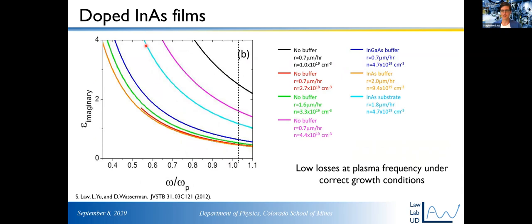And as a sidebar for any optics people who are listening, the imaginary part of the permittivity tells you about the optical losses, right? This is bad, right? You want to be able to shine light on your material and not have it be lost to heat, for example. And so you want the imaginary part of the permittivity to be quite small. And when we grow these right, which again is a little tricky, the losses can be relatively small, right? This is a reasonable amount of optical losses. So these are pretty good metals in the infrared.